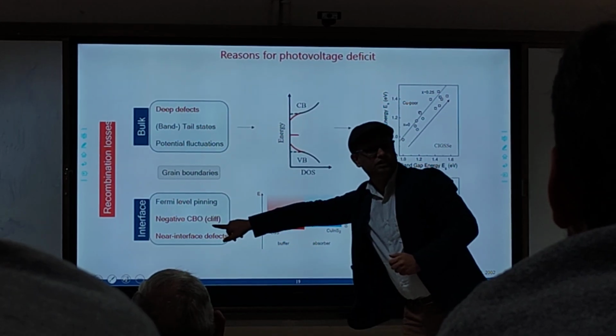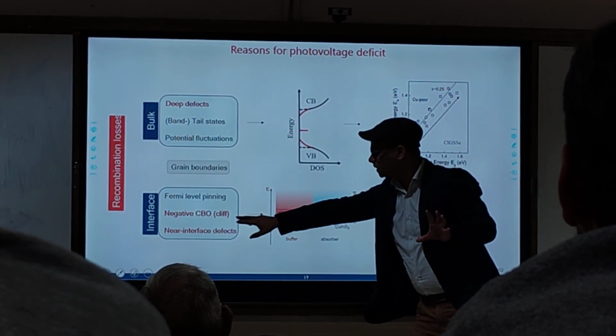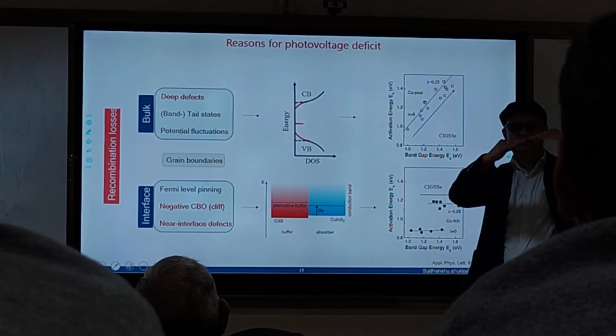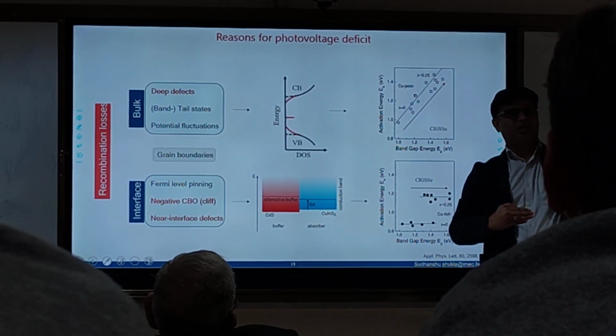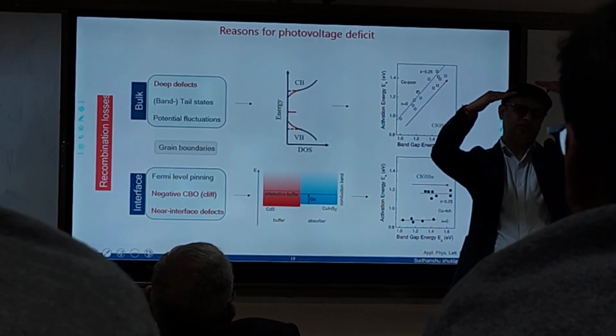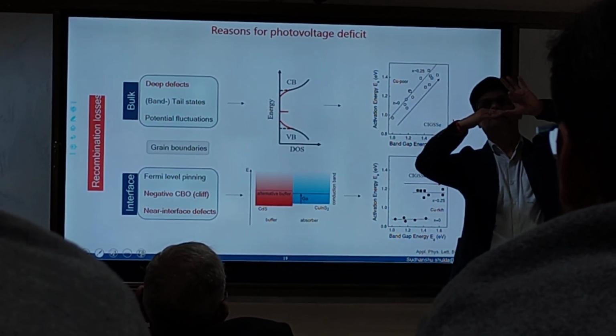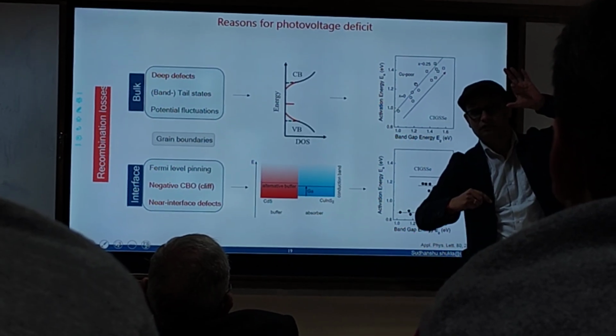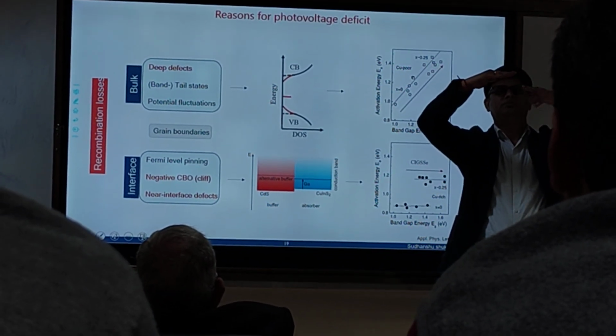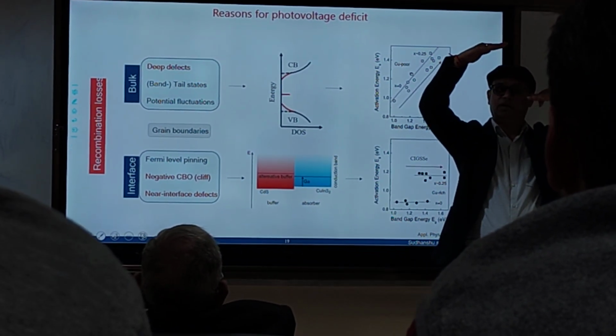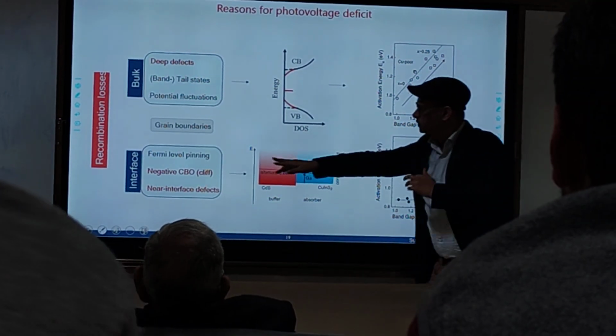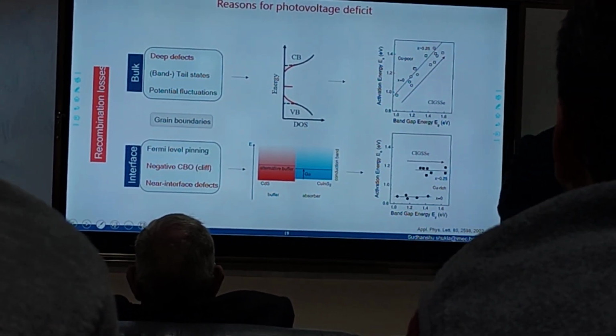You can have negative conduction band offsets. Okay, there's a little bit of jargon, but essentially this is your conduction band of your absorber. This is your N-type material. If it is low, it's a cliff. The electron loses its energy very fast. If it's above, it forms this barrier. This barrier should not be too high. So you have to do some band engineering at the interface.